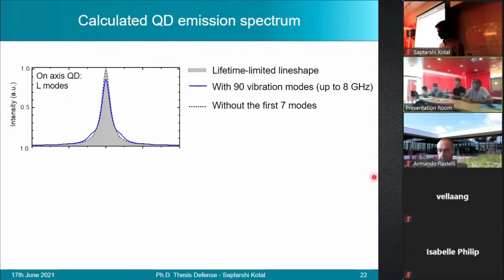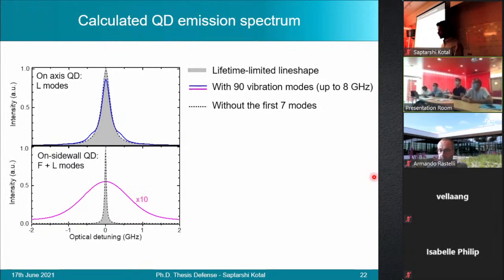Now, such a deterioration is further amplified when the quantum dot is positioned closer to the edges of this nanowire. Now they experience not only the longitudinal modes, but also the flexural ones. However, quite interestingly, we noticed that by suppressing the impact of the first 7 vibration modes of the lowest frequency, we are able to retrieve the radiatively limited line shape. And this is represented by the dotted black curve in both cases.